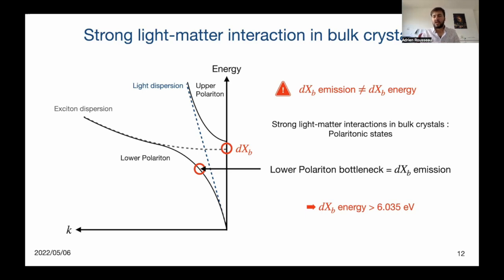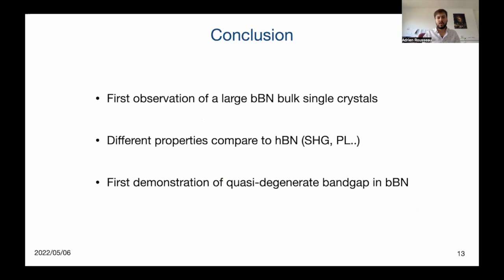Then the polaritons created during the excitation will accumulate at the lower polariton bottleneck before recombining radiatively through a direct transition. This direct transition energy will be at 6.035 electron volt. We then observe that the energy of the emission is at a lower energy than the real value of the energy of the direct exciton in Bernal boron nitride. Then the direct transition we observe at 6.035 electron volt gives only a lower bound for the energy of the direct exciton in Bernal boron nitride.